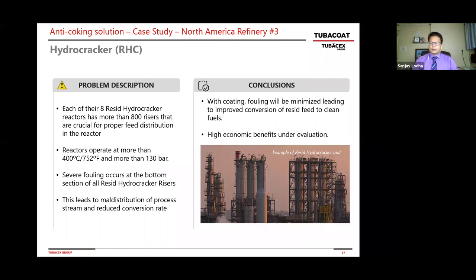This one is a resid hydrocracker, again in North America. They have 8 resid hydrocrackers feeding very heavy feed, gas oil feed, and they have close to 800 risers. Those are used for the proper feed distribution in the reactor. Temperature is close to 750 degrees Fahrenheit, 130 bar pressure.